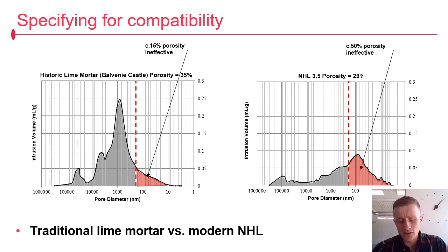I don't have time to go into the difference today, but there's a big distinction between your authentic traditional hot mix lime mortar, which you see on the left from Balvenie Castle. It's fine pored, the pore size distribution centred around that 1 micron pore size. So you set that next to a coarse pored masonry unit, and it's clearly a very effective poultice, very effective for capillary drying. So it's doing all that moisture management and your sacrificiality business, and so that's the ideal blueprint. Whereas compare this with an NHL: lower porosity, but the pore size of that porosity is the problem. So it's largely ineffective for capillary transport processes and is not as effective a poultice. So big distinction between traditional lime mortar and NHLs.